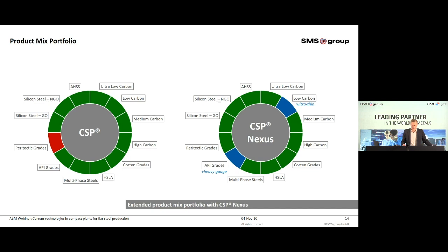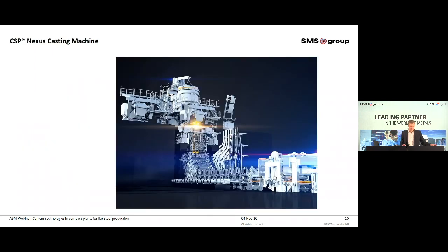Having a look at the product mix portfolio, the CSP plant can produce all typical steel grades, including silicon, multi-phase, advanced high-strength steel for the automotive industry. As you might know, peritectic grades are difficult to produce with a thin slab caster. The combination of high casting speeds and a funnel-shaped mold are not favorable due to phase transformation and the related volume change during solidification of peritectic grades. The Nexus plant is capable to produce such peritectic grades. In addition to that, it can produce ultra-thin, low-carbon grades, as well as heavy-gauge API grades up to 1 inch.